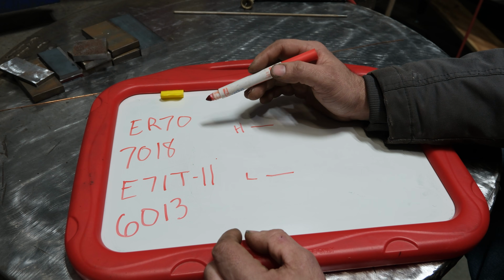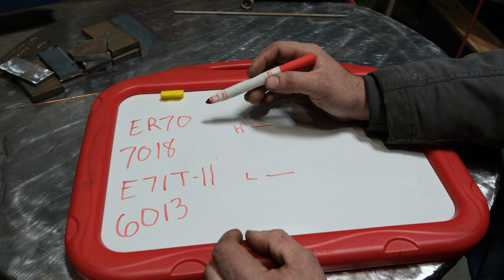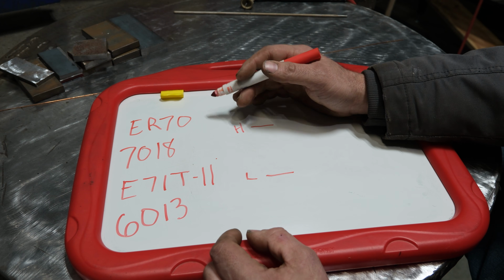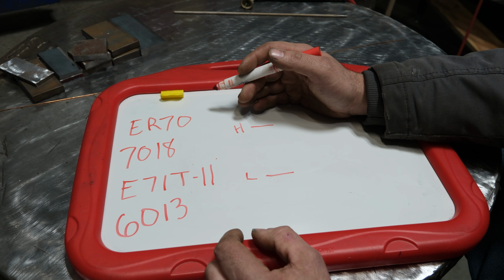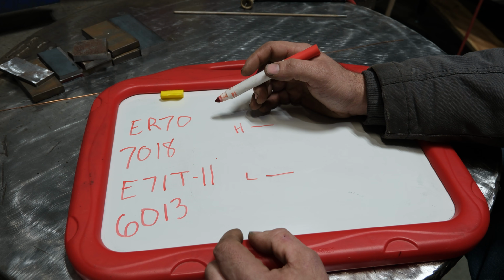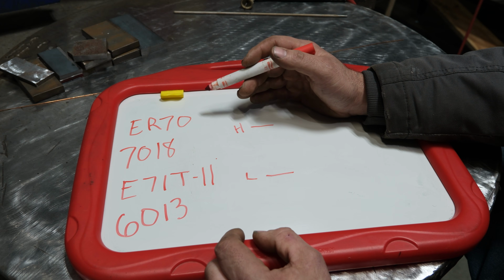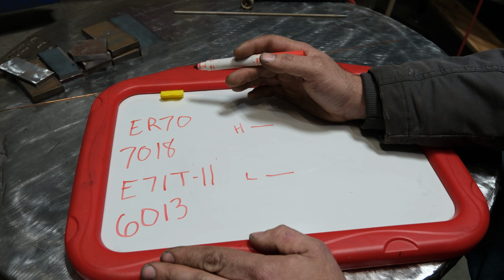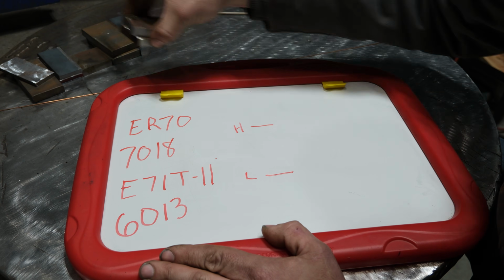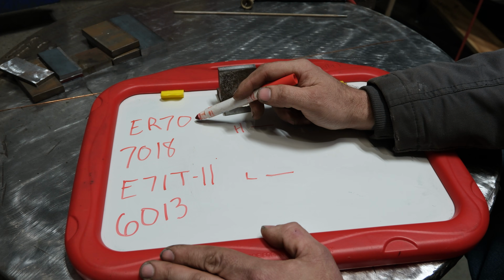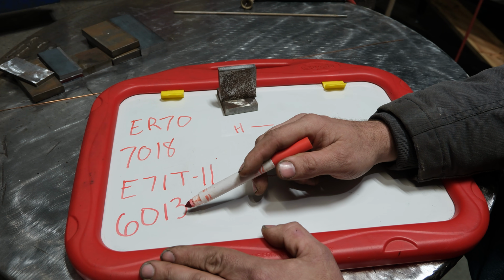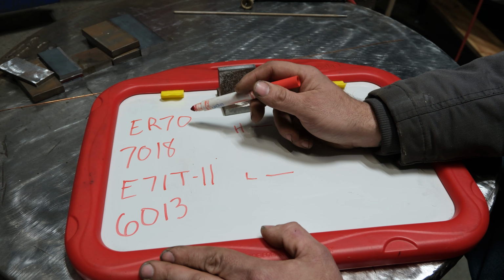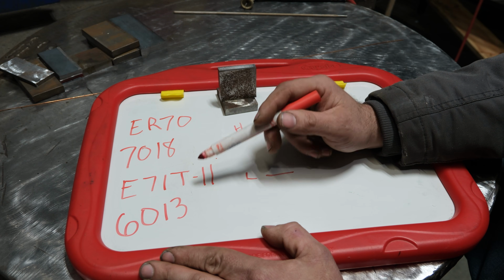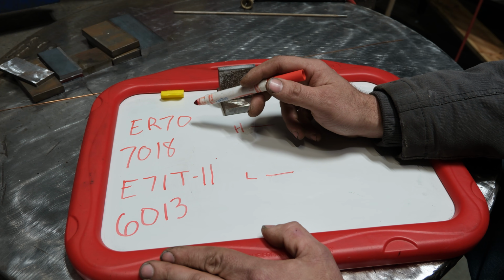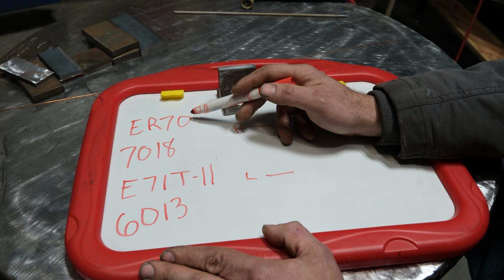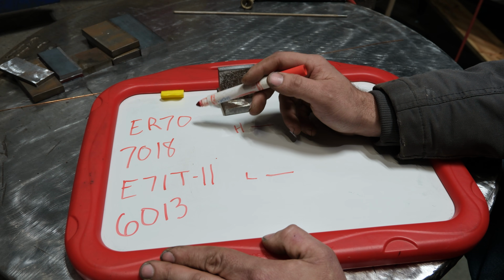The reason I bring this up is because this directly relates to a strength of TIG welding that you might not understand or realize. All of those numbers are based on a test specimen that is defect and discontinuity free. Okay, if you yourself are incapable of making a defect or discontinuity-free weld, then guess what? These are basically fictitious numbers, because what's going to be stronger in practice? A fillet weld that has a very poor MIG weld with ER70, or an extremely clean 6013 weld with no defects on it? Well, odds are, even though this is a weaker filler, it will likely perform better in the sense that all those defects come together to cause weld failure, where it isn't a limiting factor of the filler strength, it's the limiting factor of the defects of the weld.